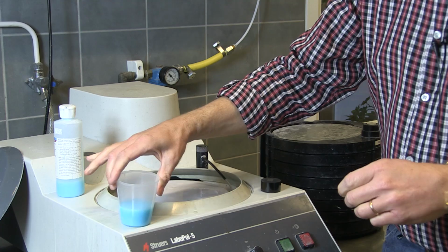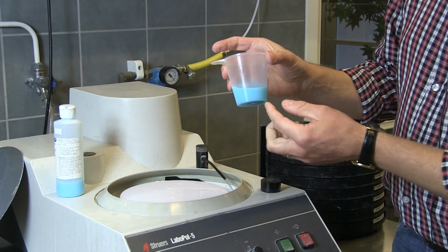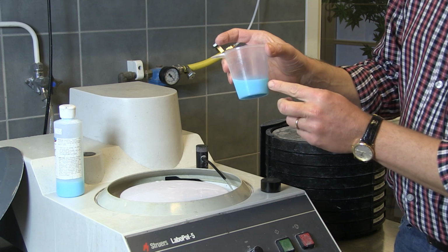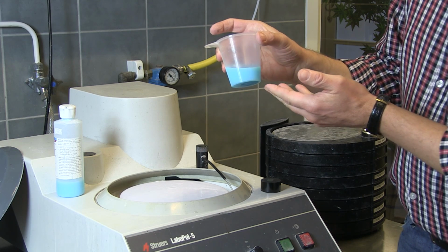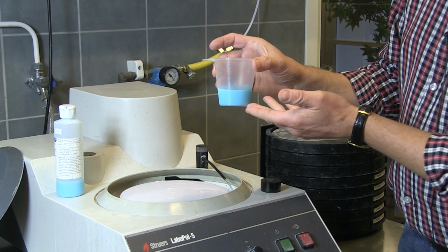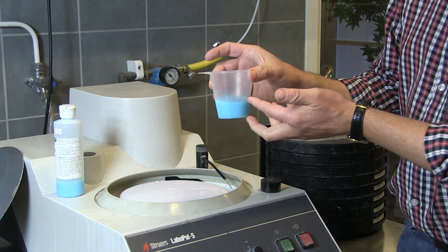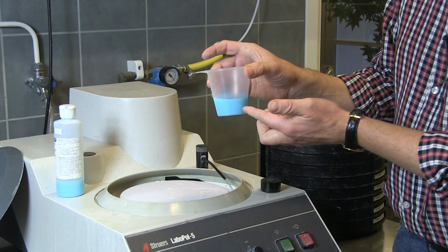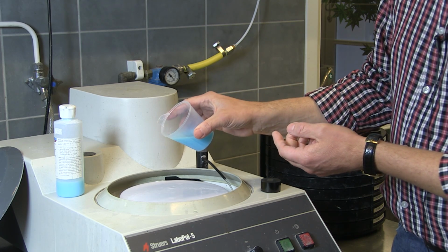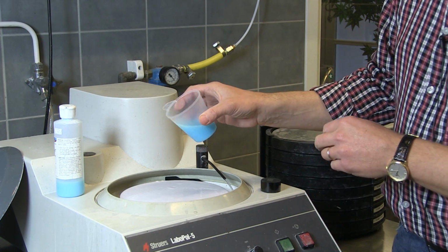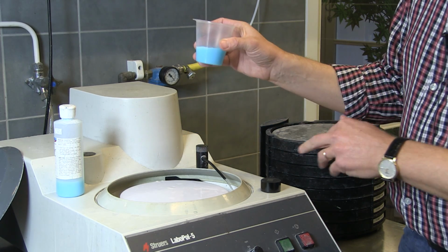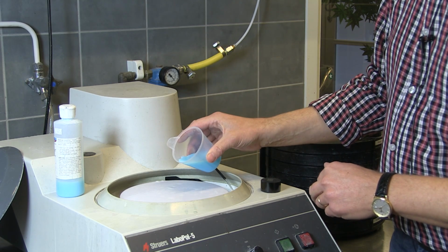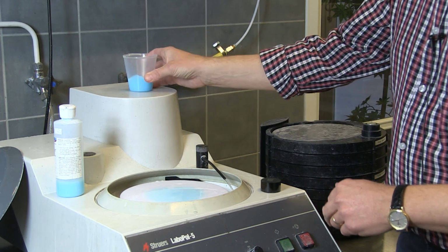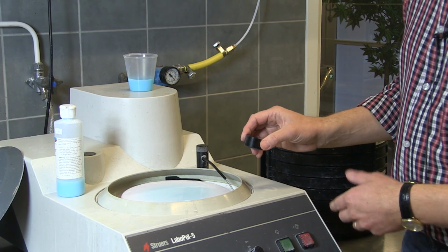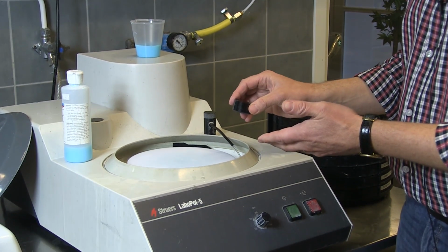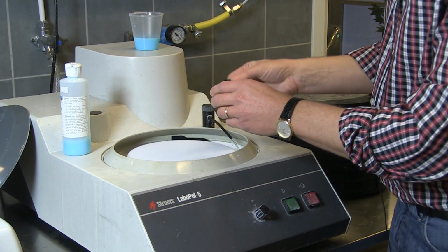And since these small particles are suspended in the water, suspended means that they are staying everywhere in this water solution. Any larger particles will be too heavy to be suspended. The suspension forces will be too small, so they will sink down to the bottom. And when I add this suspension from the edge of the cup, I will get only small particles. So, pre-wet cloth, add a little bit of the suspension, start the machine, a speed where you're comfortable with holding the sample onto the cloth, and I put it down.